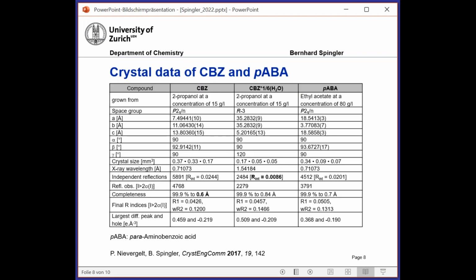As you can see on the next slide, here you will see the typical crystallographic parameters. And I want to especially point you at the R-int value of the hydrate form of CBZ, where you see, this is not a typo, the R-int is actually below 1%. I can tell you, I've done crystallography for quite some time, and it's very rare to see such a low R-int value. So it is possible to grow crystals with the crystal breeder in a very short time, and you get extremely high quality crystals, as you can see here.